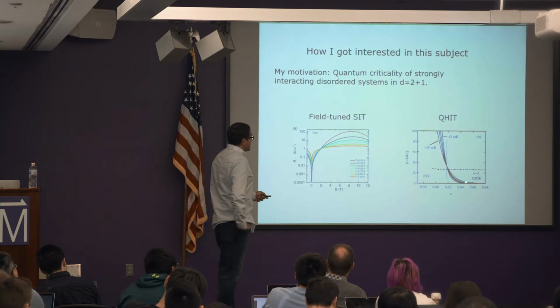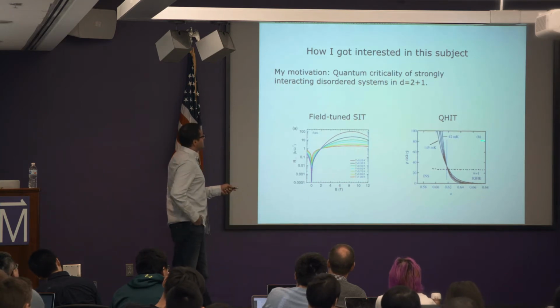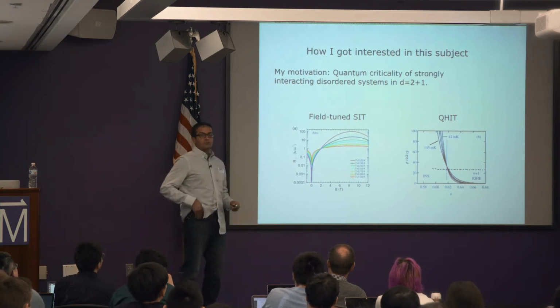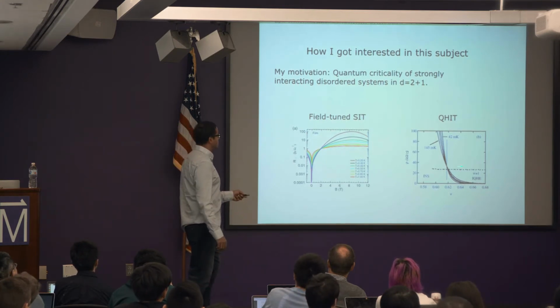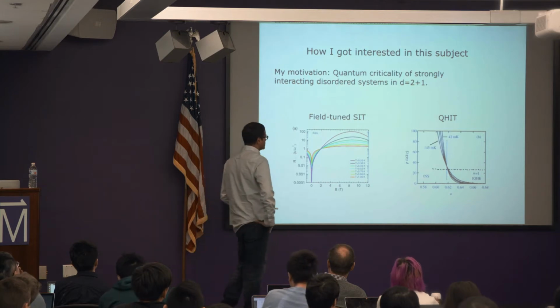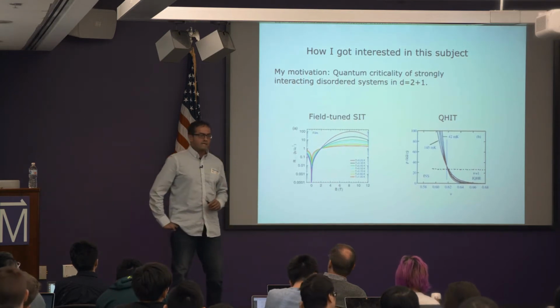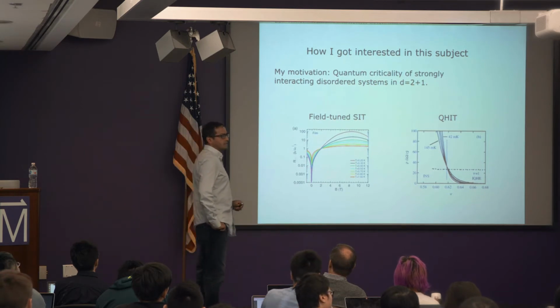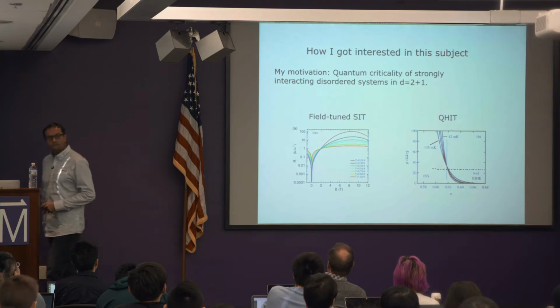And on the quantum Hall effect side, the longitudinal resistivity decreases with temperature. On the insulator side, the longitudinal resistivity increases with temperature. And the isotherms, again, cross at this quantum Hall to insulator transition, where the resistance is roughly, but not exactly, the quantum of resistance now of charge e particles, okay? 26 kiloohms.